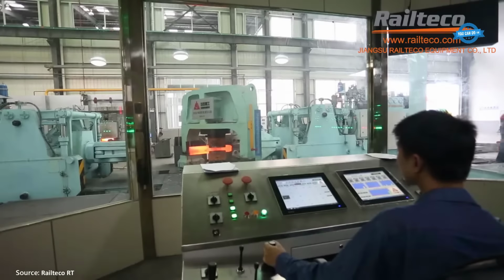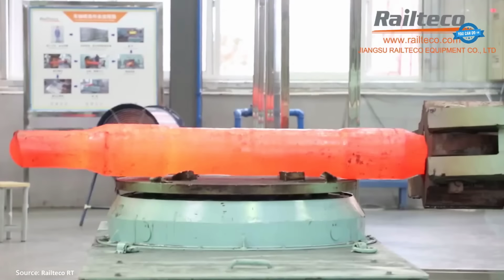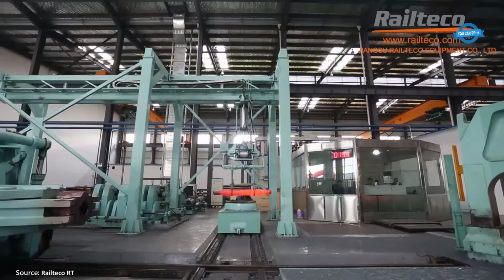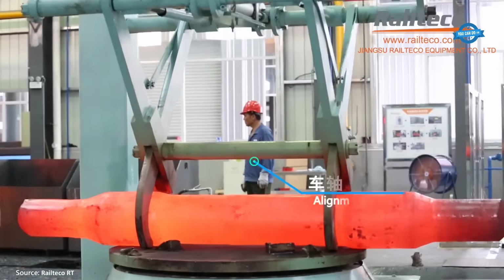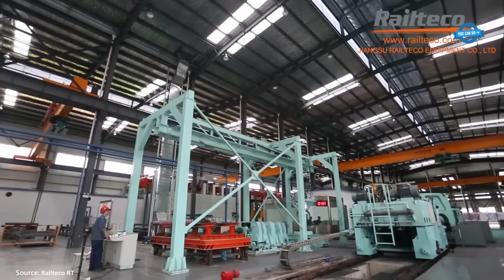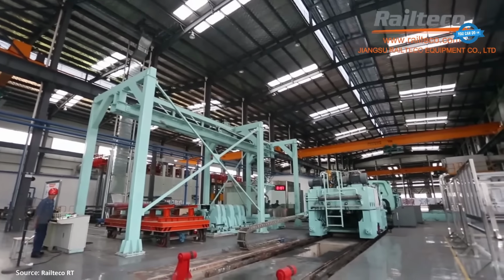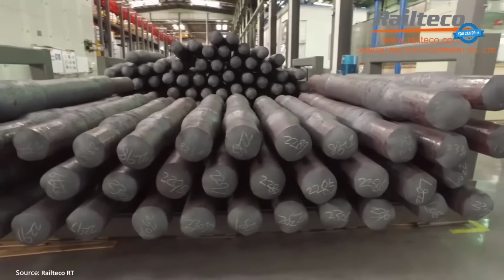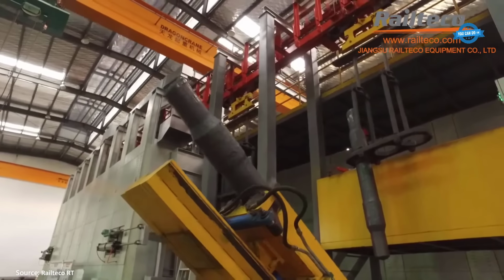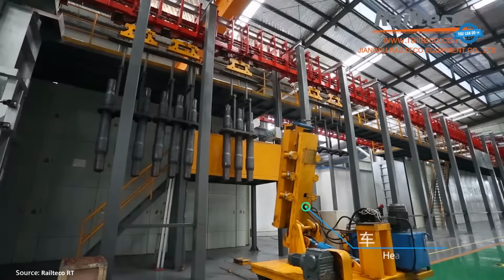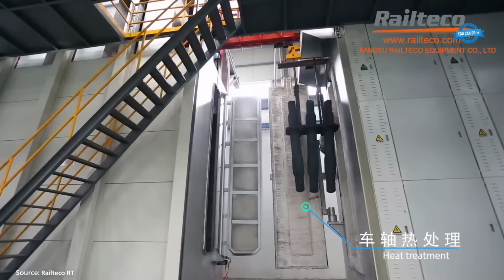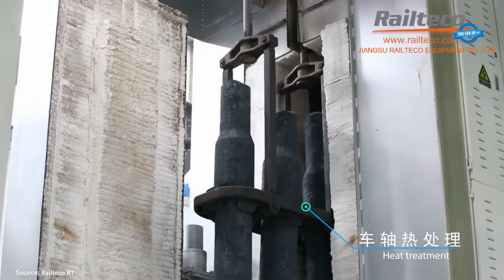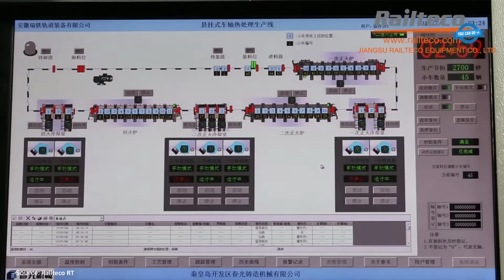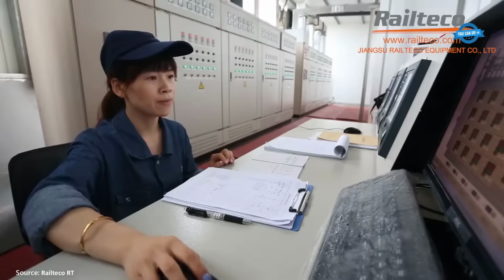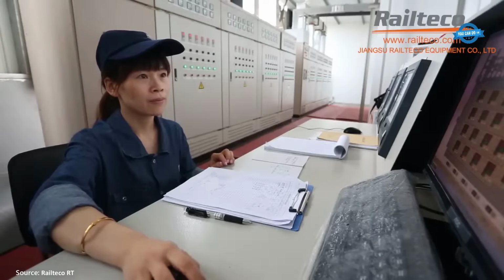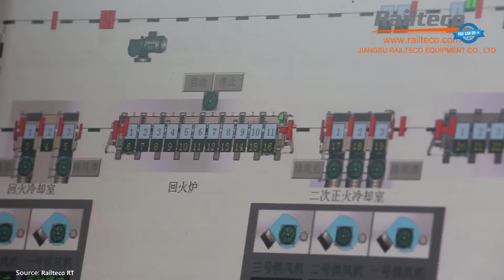After forging, heat treatment hardens and stabilizes the internal structure, improving durability. A double saw trims both ends to length. Computerized controls ensure each heating cycle is consistent, minimizing thermal stress and maximizing performance. Then it's testing time. An impact test confirms structural toughness, while spectrograph and microscope analyses dive deep into the material's chemistry and grain structure. Each axle must meet rigorous standards.